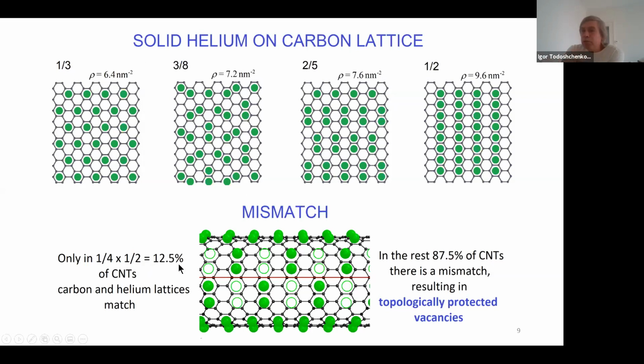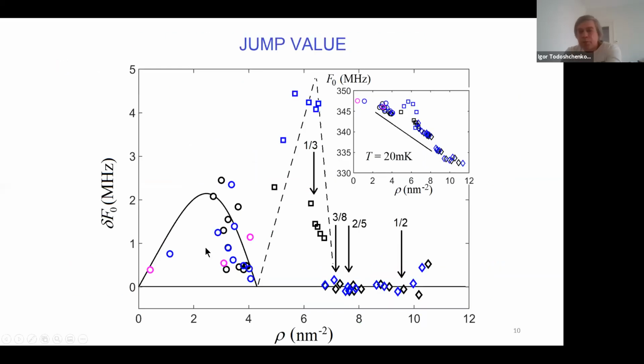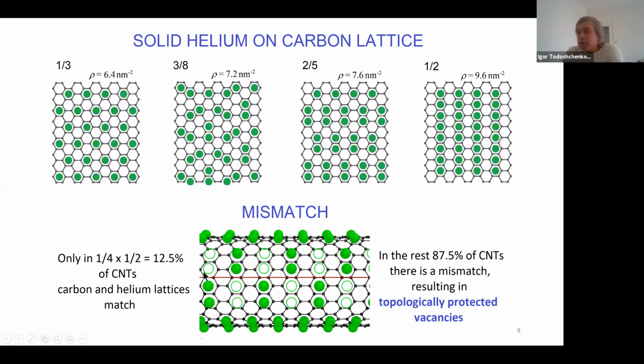So only in 12.5% of cases will the helium lattice match the carbon lattice or vice versa. If we look at this, the lattice on the top part would prefer to have dimers here, here and here, and the lower lattice would prefer to have dimers here, here, and here. But assume that there are 4 atoms in line, and this is not energetically favorable. So it prefers to create these vacancies, which are topologically stabilized, and they have zero excitation energy. They are always there. So, topologically protected vacancies.